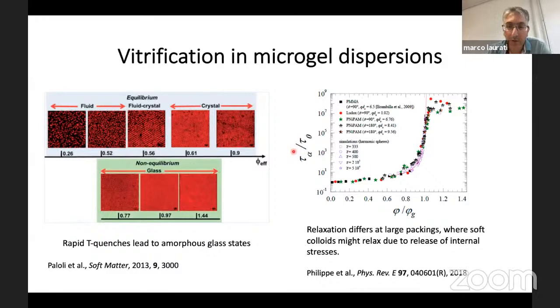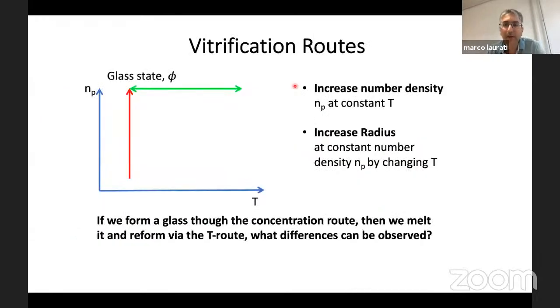So one question that we thought was not really addressed in the literature is the fact that with soft systems you can follow different routes to the vitrification, to the glass state. The one that we already mentioned is the change in temperature, which corresponds to a change in the volume fraction. But of course, you can also do what you do with, for example, hard spheres: keep the temperature constant and increase instead the number density of the system. And so the question that we wanted to address was whether the glass states that you form following one or the other route effectively have the same properties. So essentially, if you find basically the same glass state.